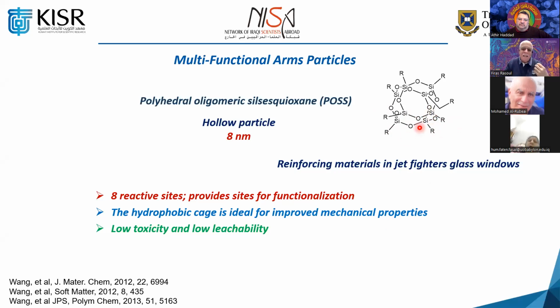As I said, we looked at it. It is a very, very nice molecule. It has 8 reactive sites, and it comes with different organic compounds. You will be able to functionalize it differently. It provides sites for functionalization, as I said. It is a hydrophobic cage, ideal for improved mechanical properties, as you see here. It has been used for this particular application. And also what we found, it has very low toxicity and leachability if you put it as part of the polymer.